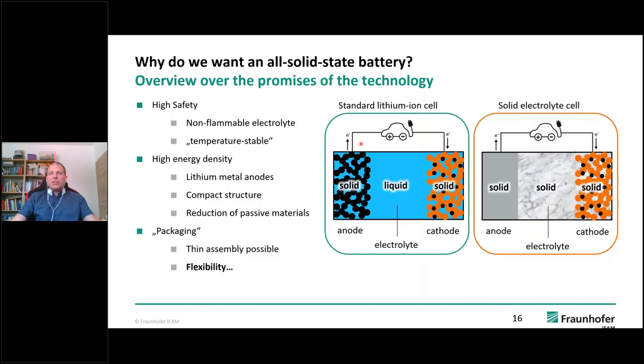So what is shown schematically here is the standard lithium ion cell. We have a liquid between the anode and the cathode side, where the lithium ions move from cathode to anode. And what we're trying to do now is replace this by a solid that is not flammable. So we have a non-flammable electrolyte, which should also be temperature stable, which is a problem for classical lithium ion batteries,